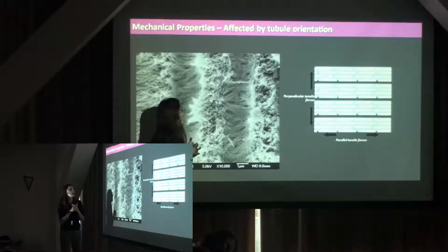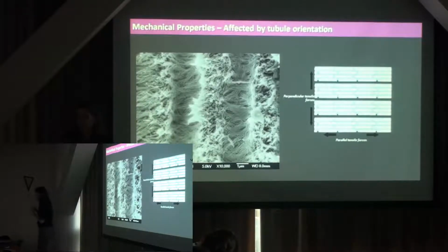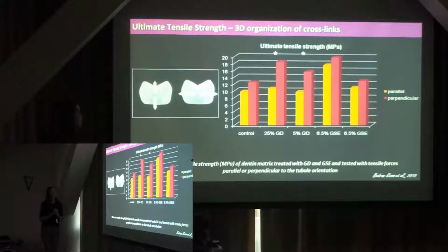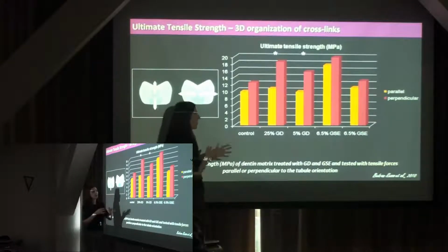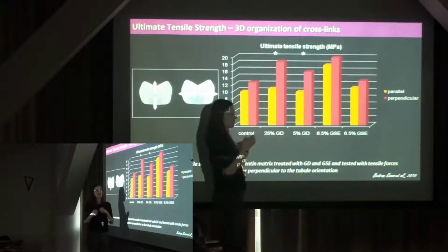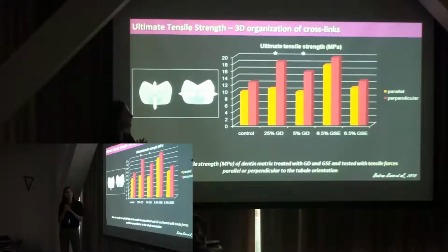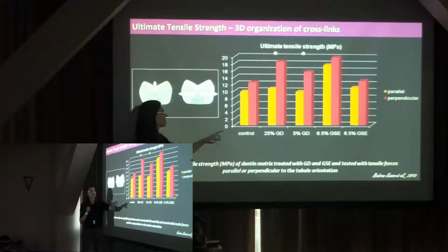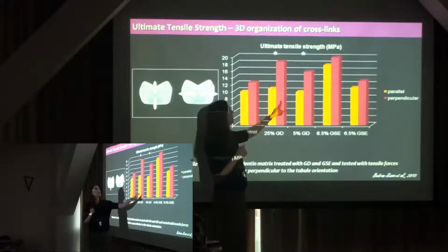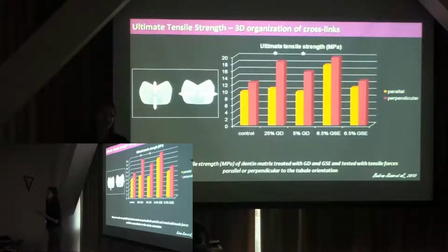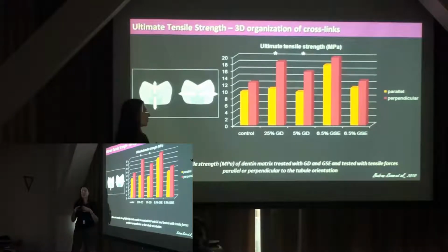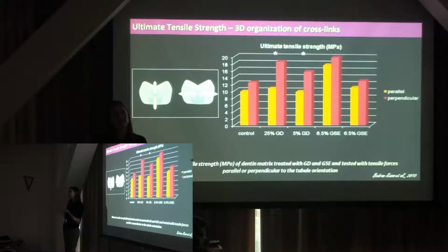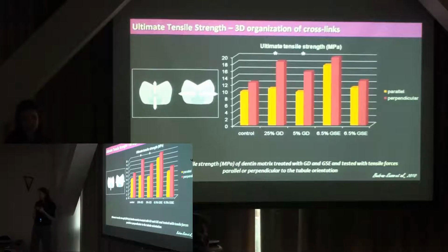So what we did is that we tried to pull them in different orientations to see if there was any variation. And what we notice is that for our proanthocyanidins here, regardless of the orientation that you try to pull this in tensile, it really didn't affect the overall ultimate tensile strength. But for glutaraldehyde, it was more pronounced on one orientation. And we hypothesized that that's likely due to the orientation of these crosslinks that are induced, that when they are in shear stress, they break a lot easier than in tensile.